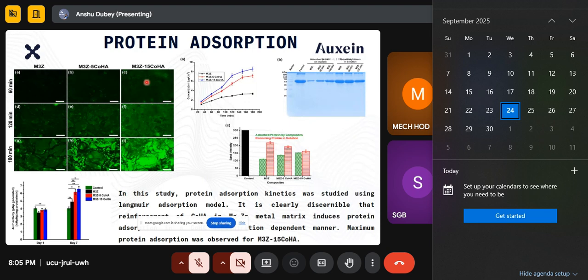So those are the nanoparticles. And then we ran the general analysis, which was similar to this image. So we confirmed the qualitative analysis and the quantitative analysis. We even did the Langmuir absorption model, and we found that it was matching with the experimental results. So the theoretical as well as the experimental results matched.